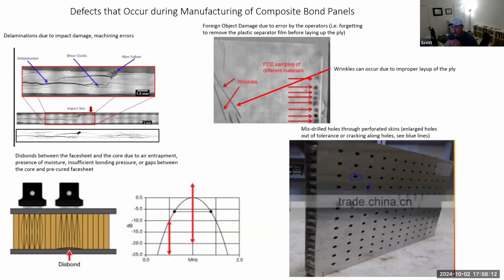There's a separation of the plies from one another along the matrix. Shear cracks, fiber failure. There's foreign object damage due to error by the operators. They forget to remove the plastic separator film before laying up the plies. Wrinkles can occur due to improper layup of the ply. During the perforation of the holes, sometimes the machine screws up, and so sometimes the holes are not in tolerance. They're enlarged, oversized holes, not per the spec. Or the holes get cracked just due to machine error.